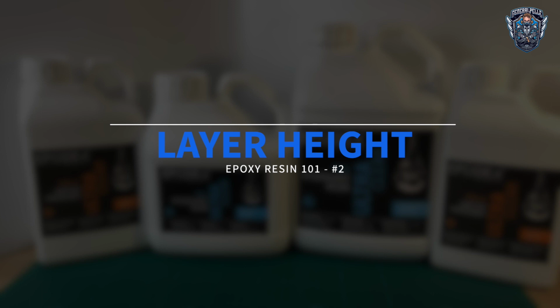If a layer is too high before it's cured, it's going to be really hot and destroy the artwork. The width and length of the area that is going to be poured aren't that important, at least for us scale modelers. The epoxy resin I'm using can go up to 5 centimeters with each layer, which is perfect for me, because I only need to make one layer. But be aware that most epoxy resin can only go up to 1 centimeter before becoming too hot while drying. So please make sure to read the instructions of your product carefully.